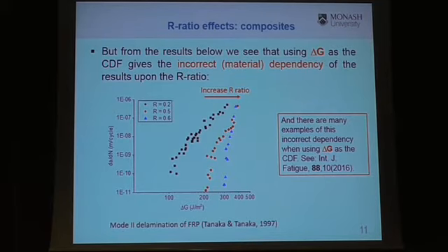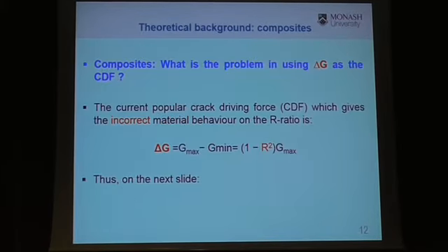And there are also other examples for this situation. So what happened for the delta G and the crack driving force? If we rewrite the delta G term in terms of R, we can see it's proportional to 1 minus R squared, and the R effect is actually being minimized as it's usually between 0 and 1.